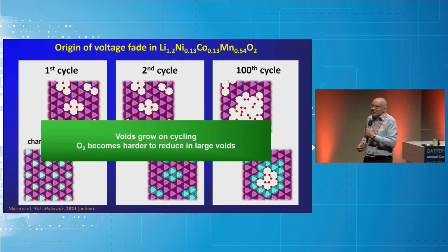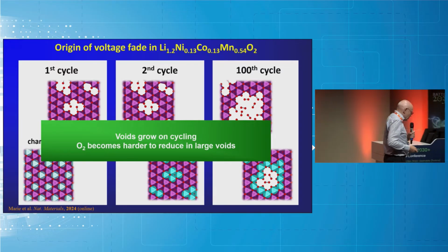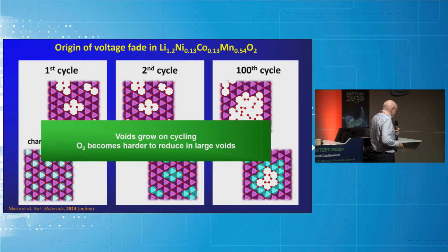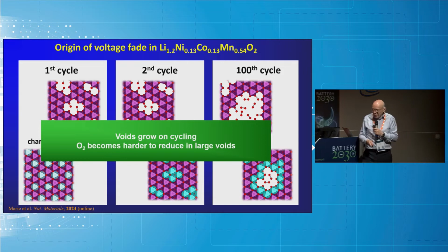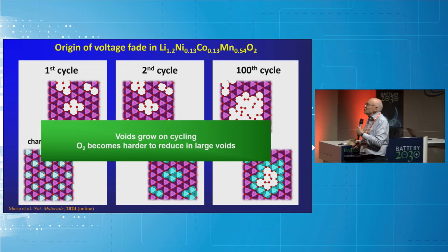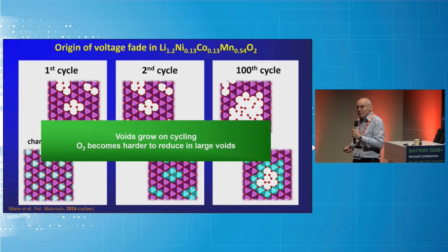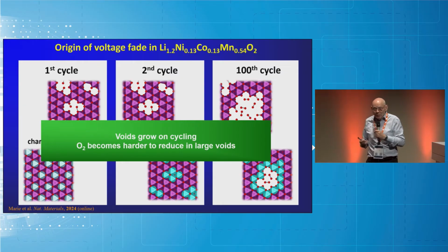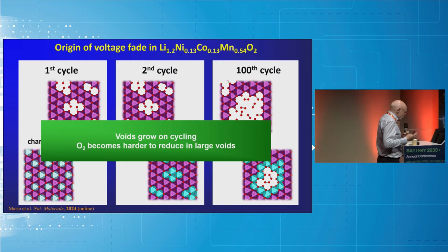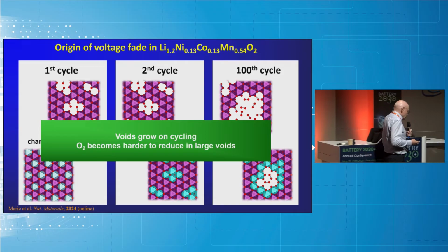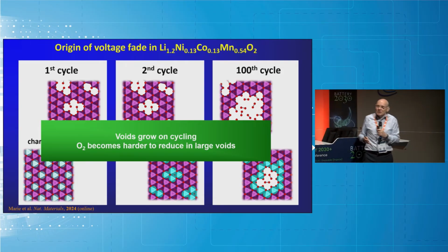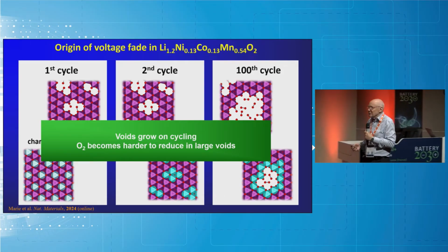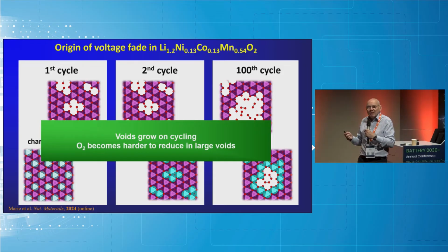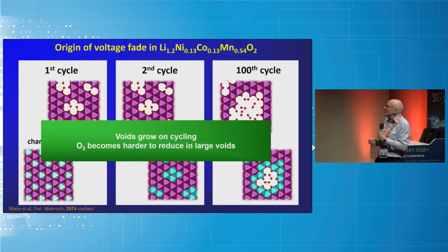What of course this means is you can spend a lifetime coating lithium-rich materials, and many people have tried, understandably, to use this process to mitigate voltage fade, perfectly reasonably. But based on this, you will reduce the amount of voltage fade by coatings, but you won't eliminate it because some of it is within the particles. So you've got to do something to stop this happening within the particles, as well as suppressing O2 loss, if you want to suppress voltage fade.